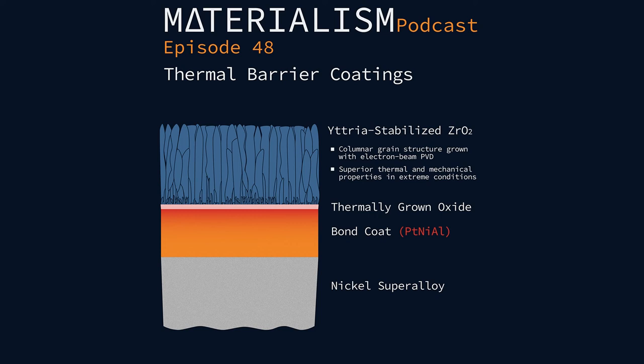Another thing they've said, well, what if we put nickel oxide in the YSZ layer? If you put it in the pores as a small amount of secondary phase, it could absorb in the infrared and then emit at a longer wavelength, or it could locally heat the material around it, right? So then you're back to conduction. So that's a pretty clever idea.